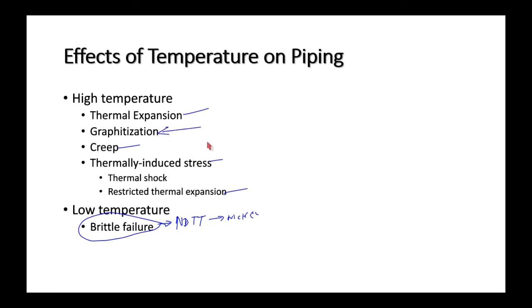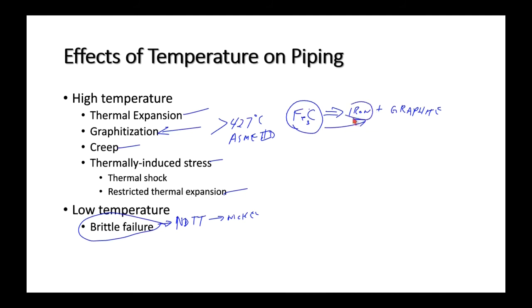What about this one here? Did we talk about graphitization? Okay, I think that in your textbook it says that graphitization occurs over 400 degrees Celsius. And I think ASME 2D says 427 degrees Celsius is when graphitization occurs, and that's when the carbide phase basically decomposes into iron and graphite. And graphite, as you recall from grey cast iron, is weak in tension. So ultimately, if we've got a particular type of pipe that's exposed to temperatures greater than 427 Celsius over a long period of time, plain carbon steel will, the carbide turns into graphite and iron, and then it becomes weak and it blows up. So it's one of the things we've got to watch out for, graphitization.